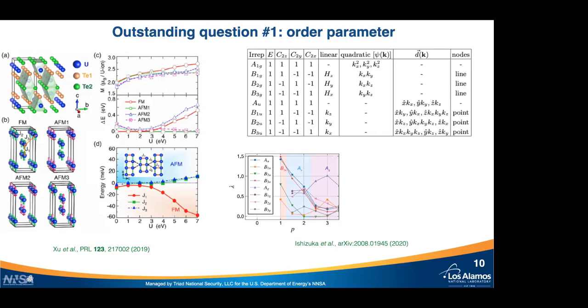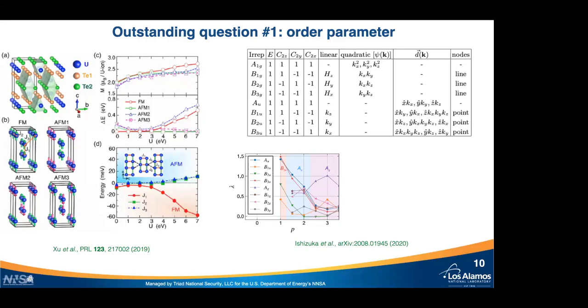And more recent calculations using a tight binding model, DFT, and periodic Anderson model, they used everything they could. And this paper is really nice. I recommend it for those of you who are interested in the subject. They take our results into account, and they do show that it's very possible and actually energetically favorable for an AG state, which is a singlet state, to occur as a function of pressure. Here, P is pressure. It's a theory paper. I have no idea what the units are here, but this is an increasing pressure regime where an AG singlet state may be favorable. So it could be that you have indeed under pressure a mixed, even and odd parity superconducting state. And this is the temperature pressure phase diagram obtained in this paper, and you can see the evolution of the possible order parameters under pressure.